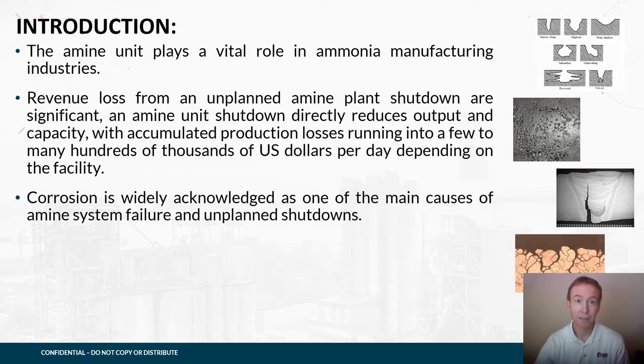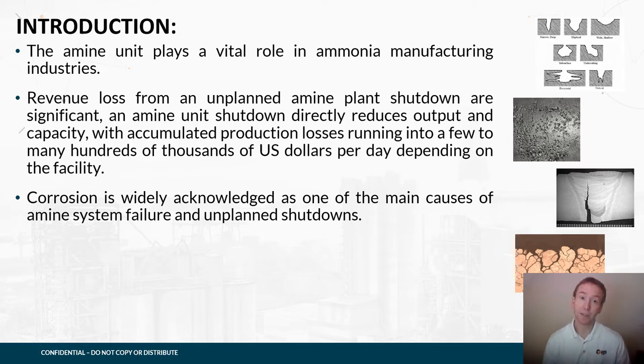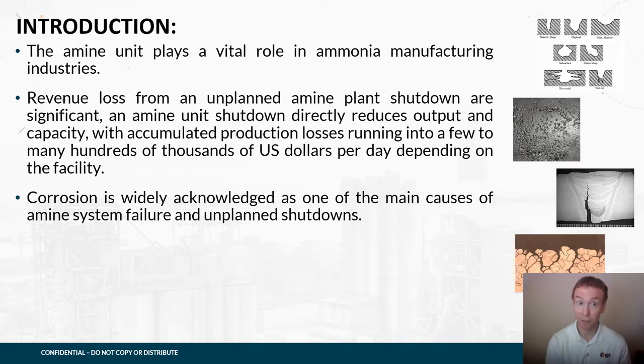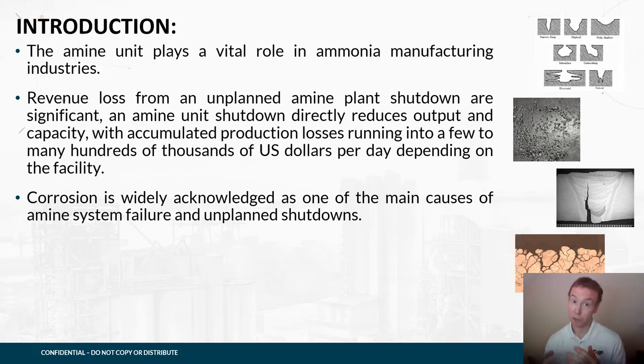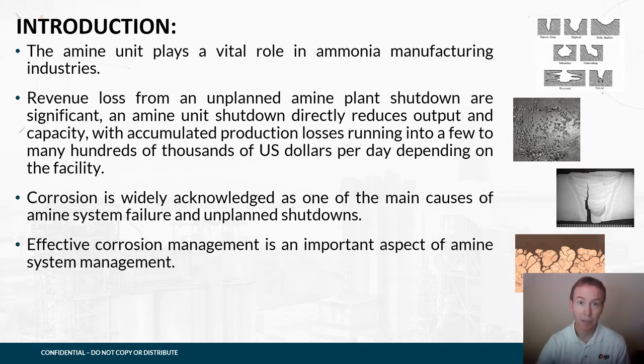Typically designed to use MDEA as the active amine, if you overload the amine this can lead to an extremely aggressive corrosion condition. If you have too much CO2 it leads to the amine being overloaded, causing the CO2 to be regenerated or released throughout the process. This can result in lots of localized aggressive corrosion conditions, and corrosion is widely acknowledged as one of the main reasons for amine system failures.